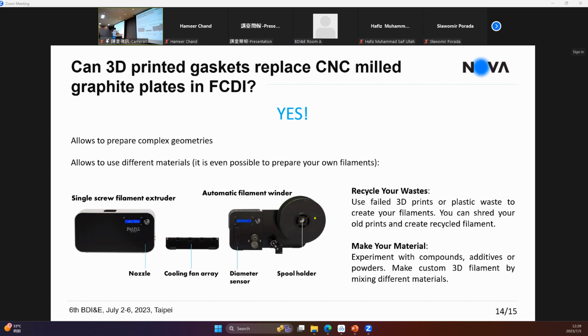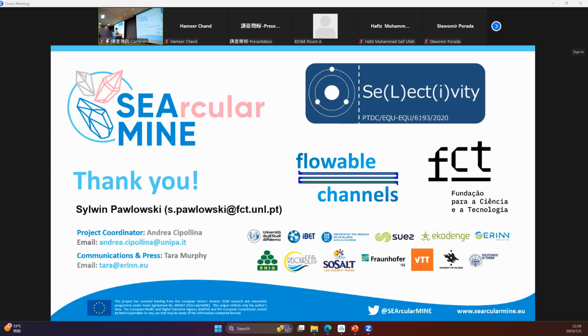Finally, you can try different materials. For example, what we used was PLA with carbon black, but obviously it was the first attempt. So if you have a filament extruder, you can prepare your own materials by mixing different materials, adding different content of carbon black or other conductive materials, and make your own filaments. So I hope that you agree with me that it's possible to replace the graphite current collectors by 3D printed materials. And I would like to thank you for your attention.